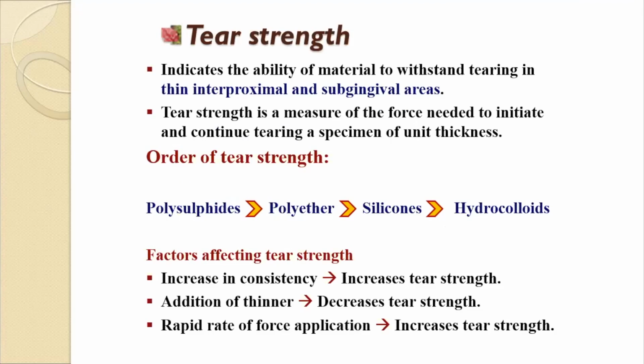Then your tear strength. Tear strength is a measure of the force needed to initiate and continue tearing of a specimen of unit thickness. So it indicates what? It indicates the ability of the material to withstand tearing in thin interproximal and subgingival areas. So your polysulfides have maximum, then your polyethers, then your silicones, then your hydrocolloids. The factors which affect your tear strength are: increase in consistency increases the tear strength. Addition of thinner will decrease your tear strength. Then rapid rate of force application increases your tear strength.